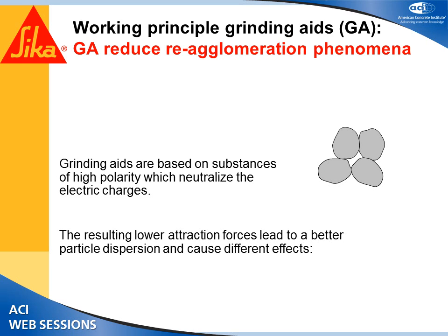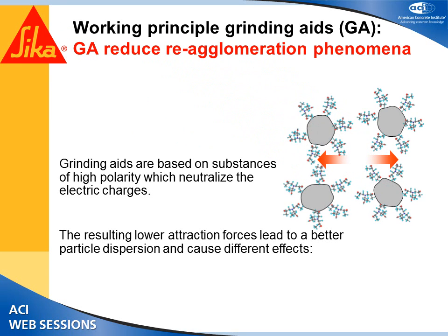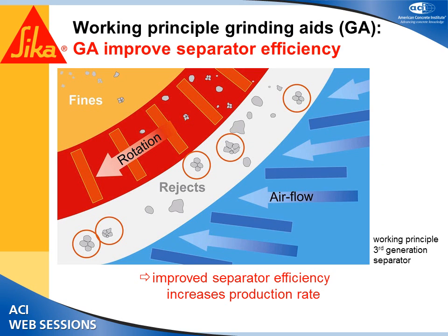The third thing that grinding aids do is, whenever clinker particles are broken, they have a tendency to form agglomerates or come together. Whenever you are using a grinding aid, it basically disperses those agglomerates. The problem with the formation of agglomerates is when the material is grinding and moved to the cement separator, where the cement gets separated, the finer particles go to the bagging area, and the coarser particles again go for grinding.